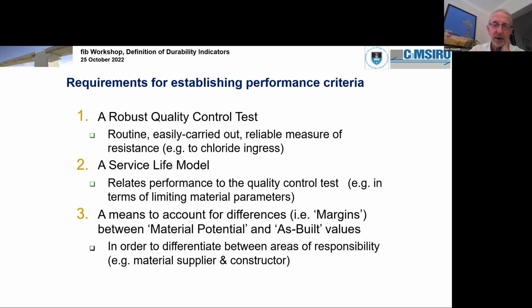We must be able to account for what we call margins or differences, because you get what we call a material potential. That's what might be produced by the ready mix producer. And the as-built values, invariably, the as-built values in the real structure are lower or of lower quality generally than the material potential, which is what the ready mix producer produces. And so to differentiate between areas of responsibility, and hence also a question of payment items, those two have to be differentiated as well. Otherwise, you're continually having conflicts between these issues.